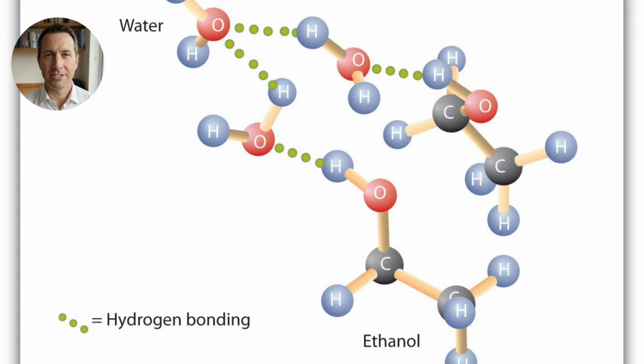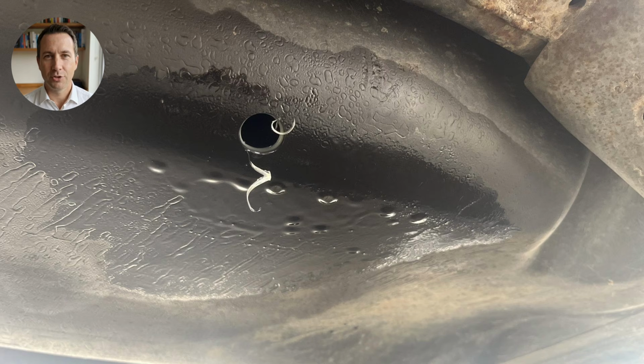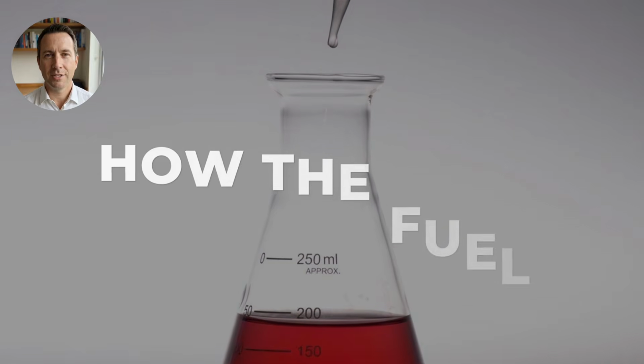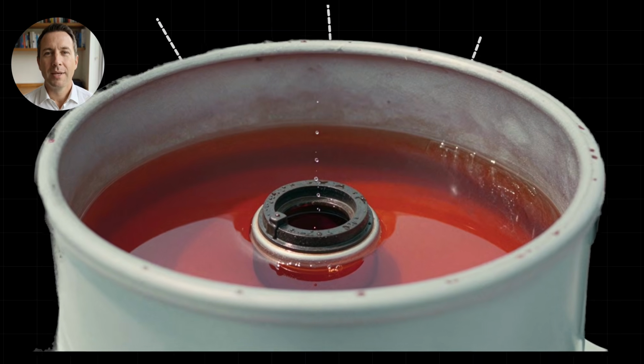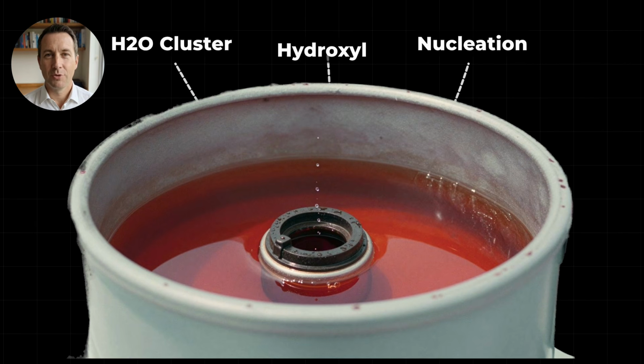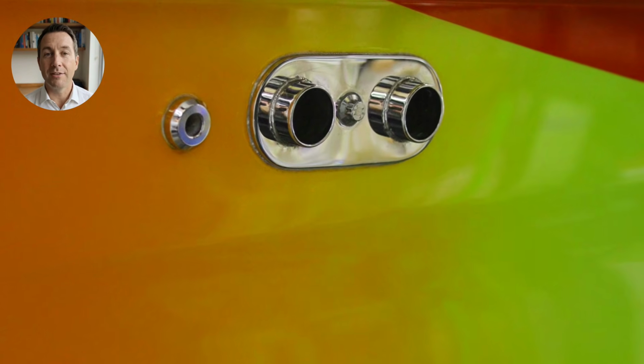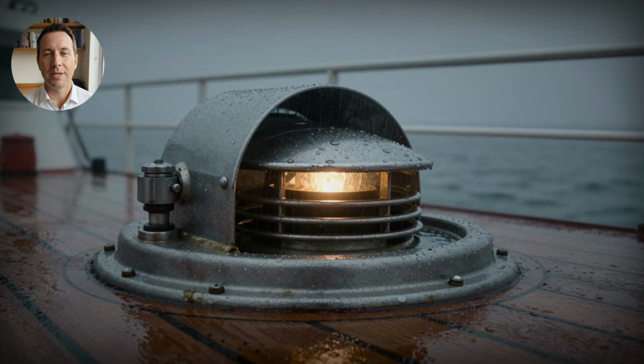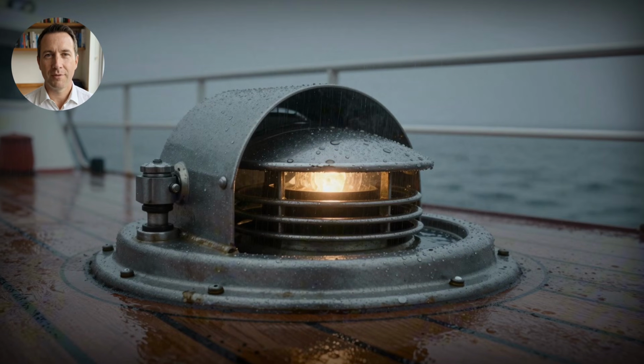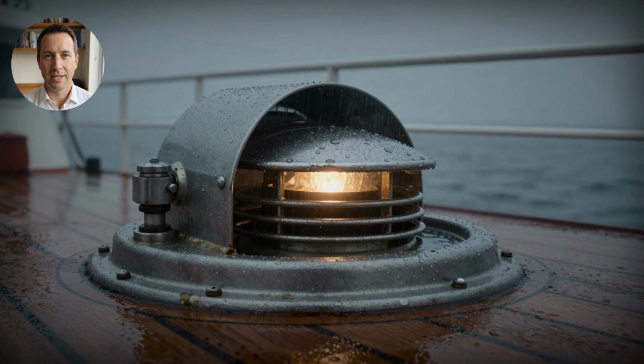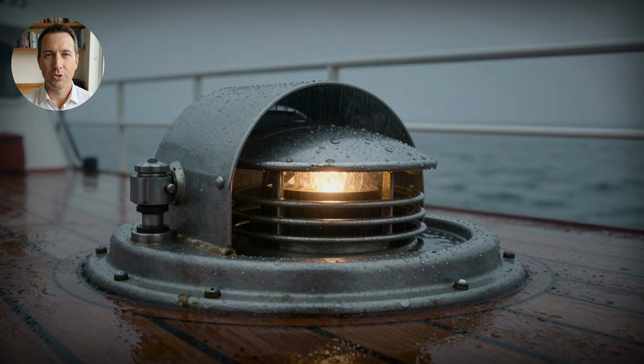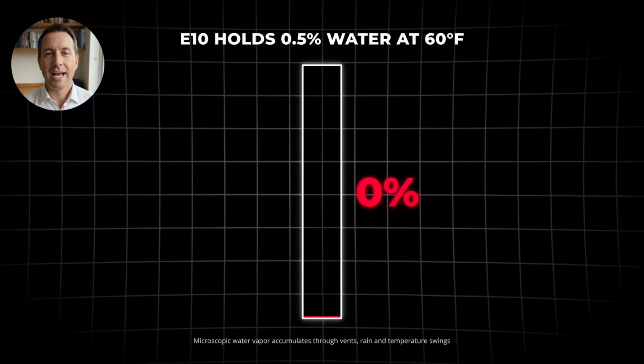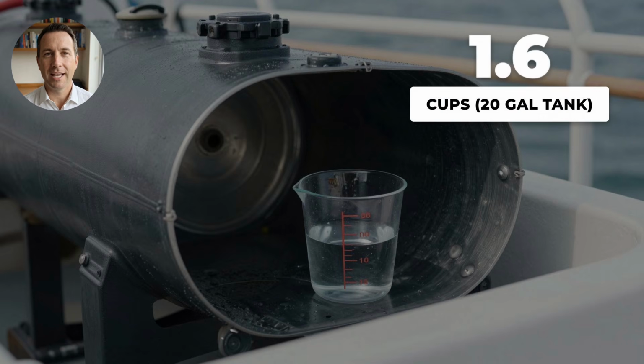The chemistry behind this is not complicated, and that is what makes it so dangerous. Ethanol is hygroscopic. The hydroxyl group in the ethanol molecule attracts water from the surrounding air. Your boat's fuel tank is vented to the atmosphere by design, which means every humid day, every rainstorm, every temperature swing between night and morning is pumping microscopic water vapor into your fuel. A 10% ethanol gasoline can hold roughly 0.5% water by volume at 60 degrees before it reaches its limit. In a 20-gallon tank, that threshold is about 1.6 cups of water.